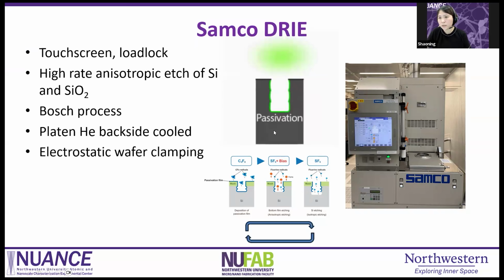So basically, this is an alternating of etching and passivation process. The etching process is using SF6 gas plasma and etches a little bit through your silicon, and it will quickly go to the deposition process, coating a passivation layer using the C4F8 gas in the plasma environment. It will coat a very, very thin layer of protection over all the surface: flat, vertical, and the bottom of the trench. Then the process quickly switches to etching again with SF6 and the bias signal.